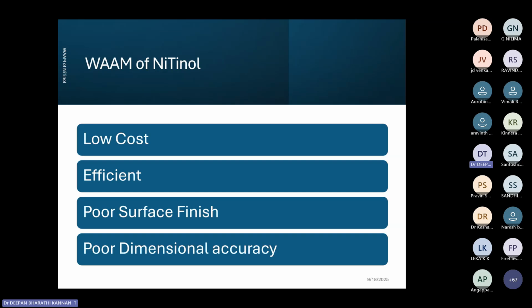And with respect to stainless steel also, the wire cost is around $15 per kilogram, whereas the powder cost is around $45 per kilogram. So it is almost 3 times higher than the wire. So economic aspects are one of the main priorities. Then I think wire additive manufacturing could be explored with respect to nitinol shape memory alloys.